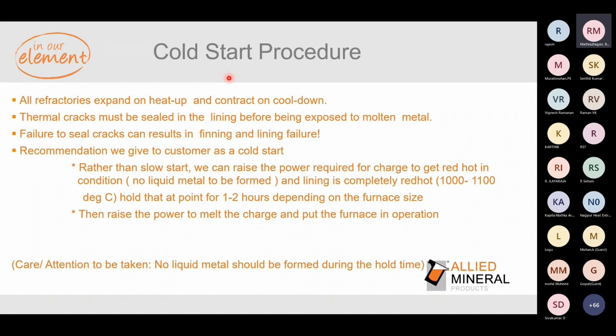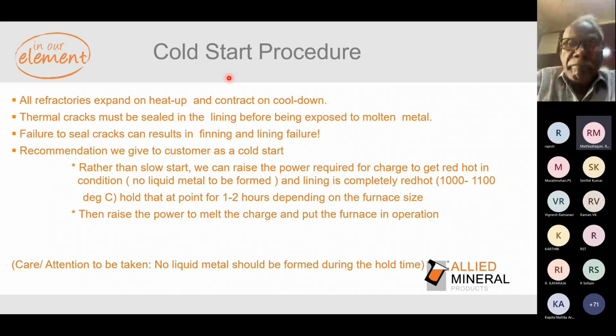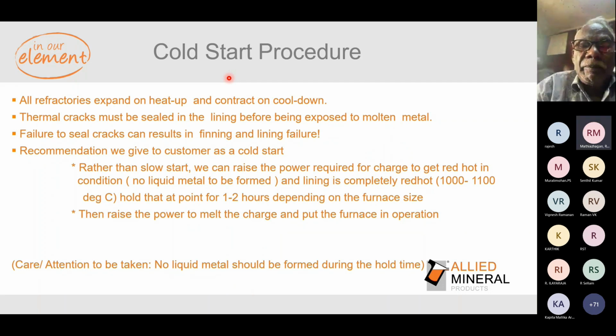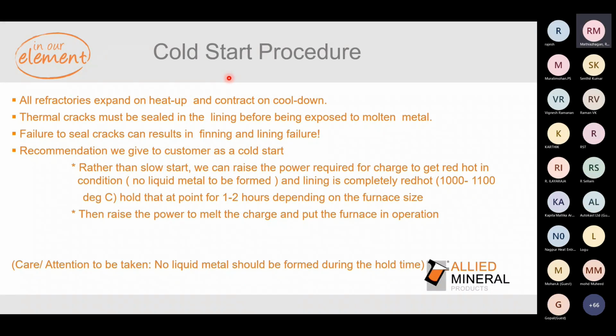If you're going to do a slow start, you think actually you're giving a slow start, but you're not giving a holding wherever is required, and then you're trying to melt, and this will allow the metal to penetrate into whatever cracks were developed during the cooling process. So holding is important. Hold for 1 or 2 hours at red hot condition for the refractory to expand and seal up, to avoid any kind of finning happening.